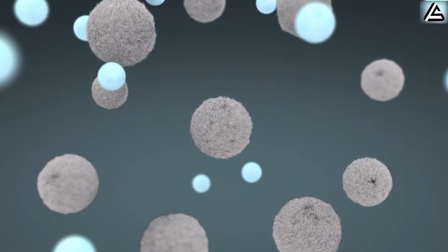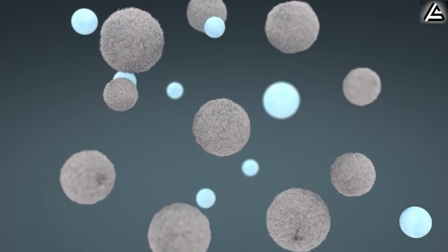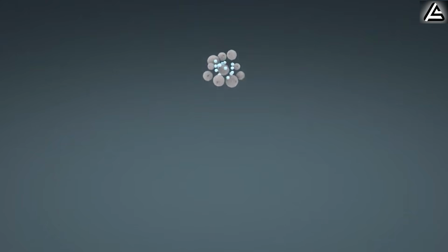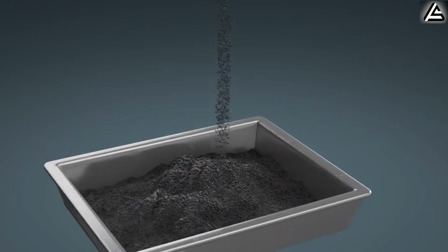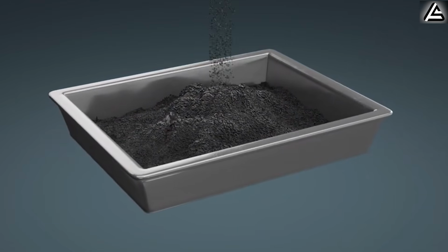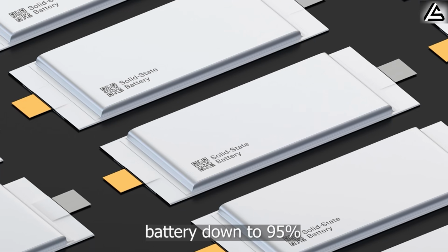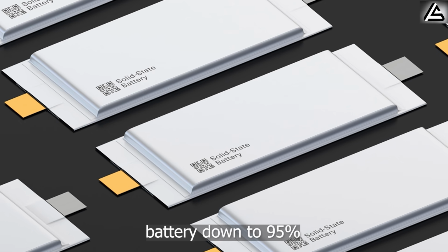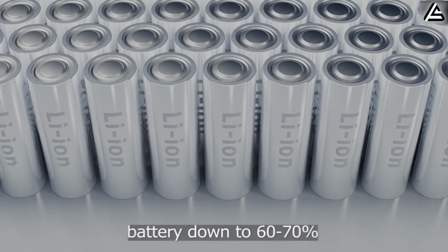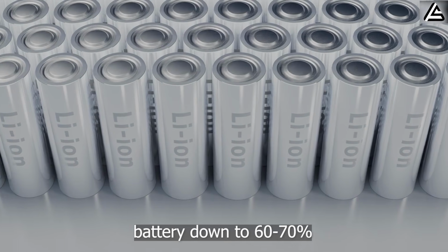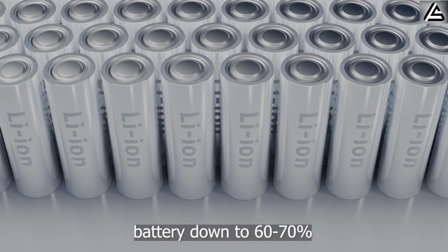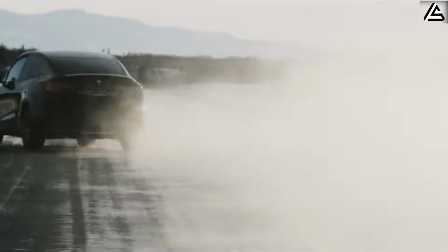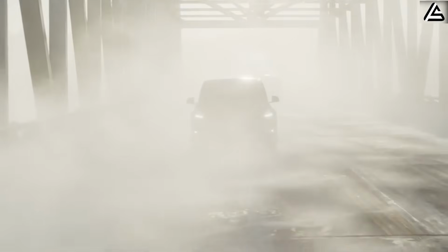Come back to the solid electrolyte. It acts as a thermal insulator, preventing cold from penetrating into the battery's core. This maintains a stable internal environment, critical for consistent performance. Even after a night in negative 20 degrees Celsius, a solid-state battery can help your vehicle retain 95% of its charge, while a lithium-ion counterpart would see a significant drop of 60 to 70%. This reliability means that you don't have to worry more about range and acceleration on frosty mornings.